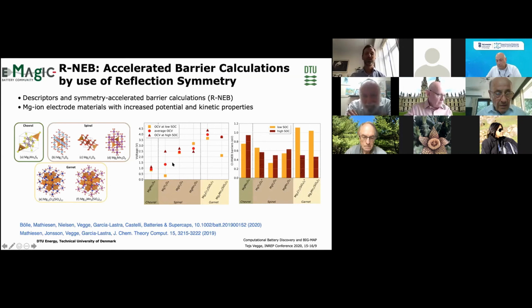I also showed a few here where you can say, not so much the thermal heat generation, but oxygen evolution, for instance, which was also mentioned by the previous speakers. Those approaches can allow us to detect the onset of oxygen evolution as a function of lithiation, for instance. Similarly, for the thermodynamic heat release, we can also do that. But it depends a little on the complexity of the material. If you have a highly disordered material, it gets much more complicated.